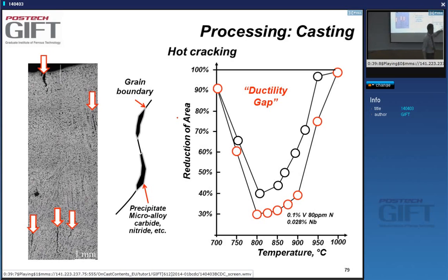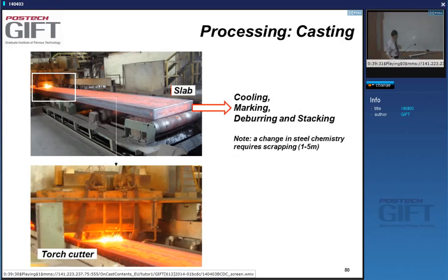But these are the kinds of temperatures the slab is exposed to, for instance, at the surface. And so this can also give cracks. In really bad cases, the cracking can even be inside the slab. So, hot cracking. Okay, so this is what comes out here. Again, the slab looks nice and straight, but don't forget it's been bent and unbent, and then it may have cracks at the surface.